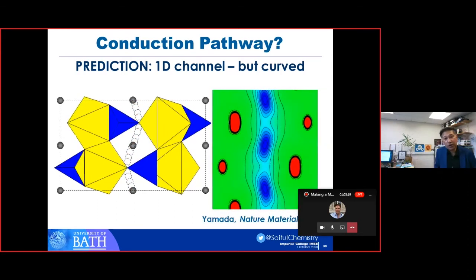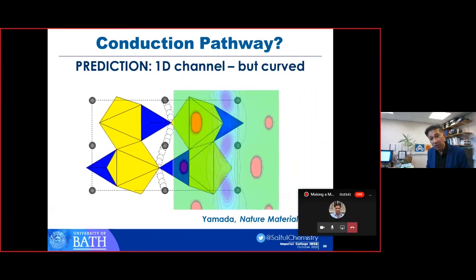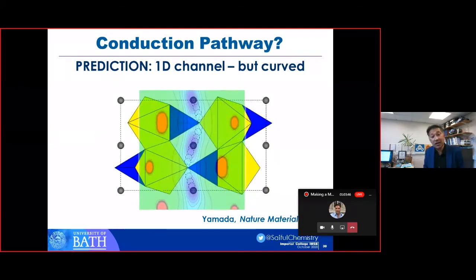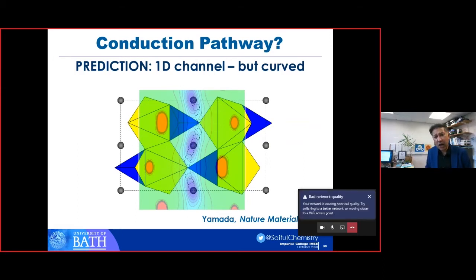And what was nice is that a few years later, there was some elegant experimental work in Tokyo, which also showed that it was a 1D conductor, and from their elegant diffraction work, that it was a curved pathway. So from our modeling, we've shown both quantitative and qualitative agreement with experiment. And that's shown, if you do an overlap, that we actually predicted the curved pathway quite nicely. And we've done this for a range of different materials. I won't go through all the materials that we've looked at, but we've done this for a range of other cathode materials. So that was confirming the prediction.